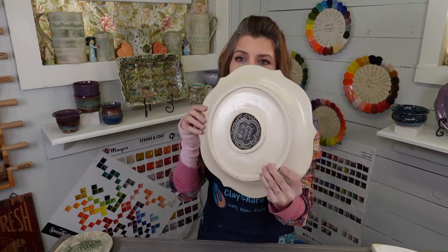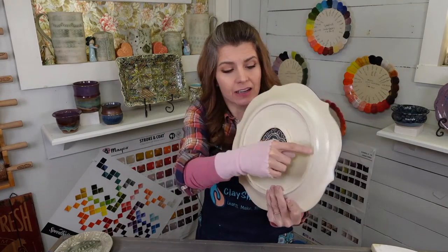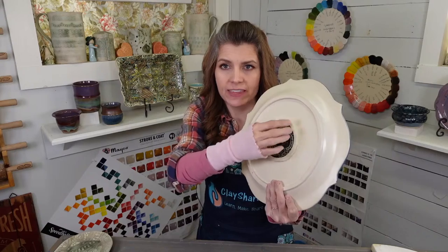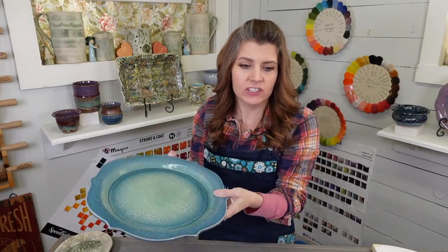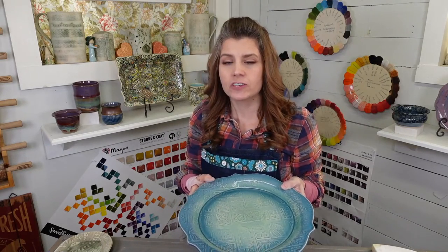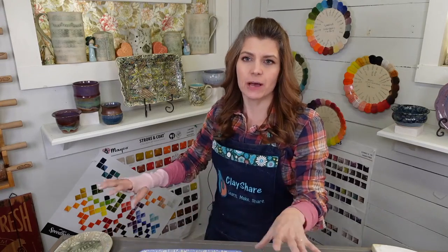The best thing to do when making plates to alleviate slumping touching the kiln shelf is to put an extra foot ring, or if you want to do an X on the back, you could — just make sure they all meet at the same height. Can you rehydrate slightly in the beginning stage of slumping? You can try, but often trying to flatten it back out it'll crack. I've come in the studio, seen a piece that I forgot to weigh down, saw it bowing up, wet it down a little bit, pressed down on it thinking I could, and it just snaps. It rarely works.